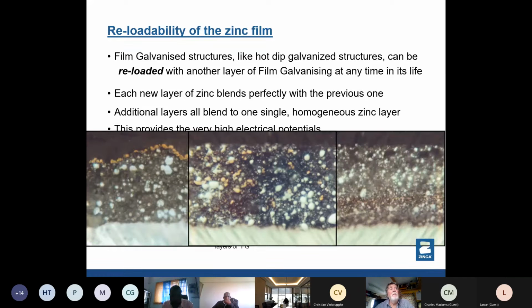Okay. So you can see the zinc particles here. That layer on top is actually a layer of gold dust on the surface to show you the top of the first layer. They've applied a second layer, and you can see it's mixed into 1 single layer because the gold dust is mixed right through the 2 layers. And on the end there, that is zinc paint. You can see the gold layer in the middle. So there's 2 layers there split by the gold dust to show you there's 2 separate layers with no conductivity and no voltage protection.